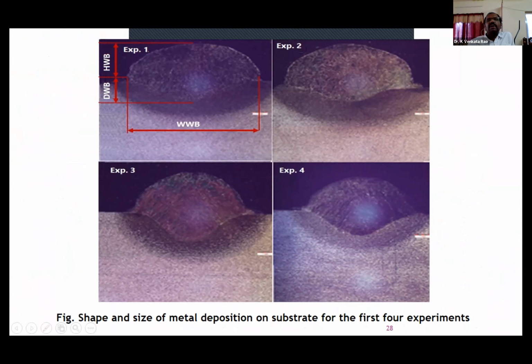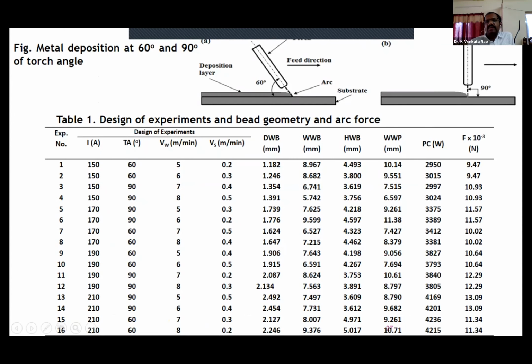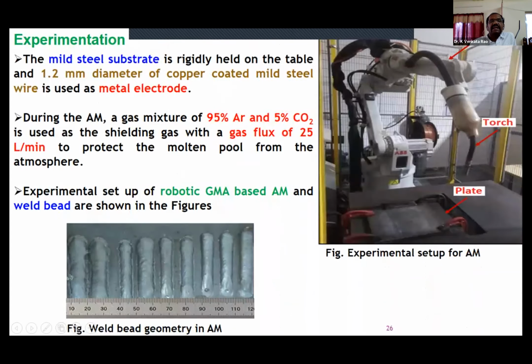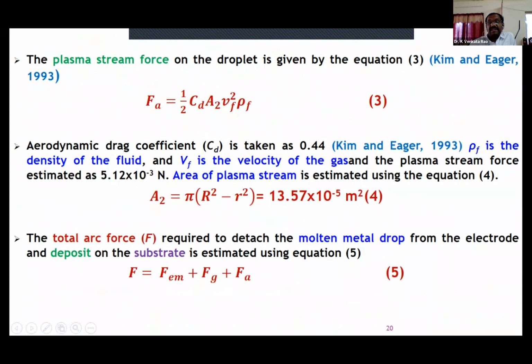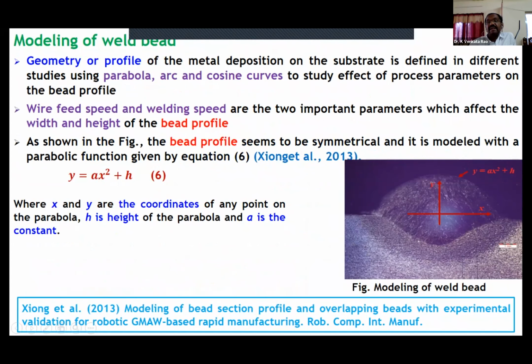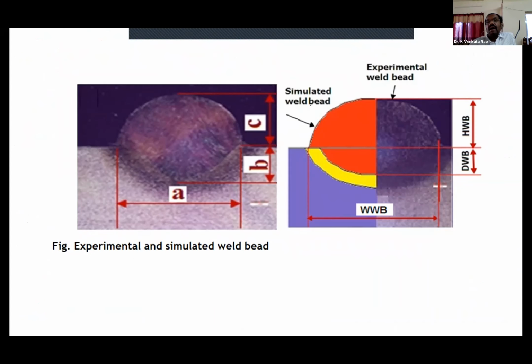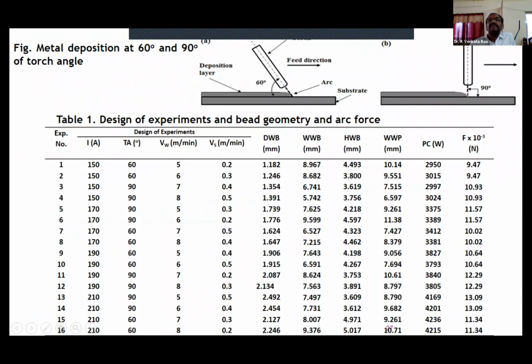These three were measured. These are the weld beads under the microscope for the first 4 experiments. So like that we measured the 3. This is PC. This is power consumption we measured while the experiment was going on for the 16 experiments. And this one is the total arc force. F is the total arc force estimated using equation 5. Using equation 5, we estimated the arc force.